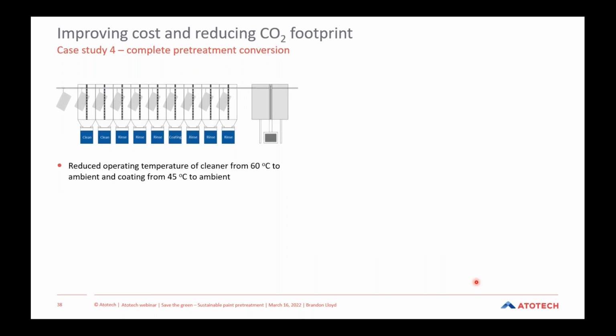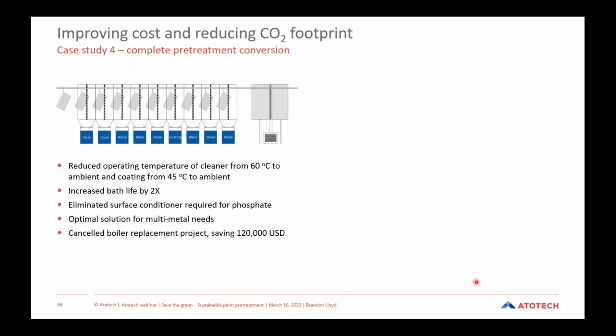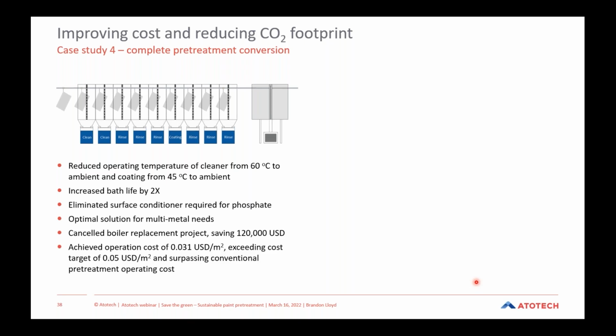With this, they were able to reduce the operating temperature of the cleaner from 60 C to ambient, and for the coating from 45 degrees C to ambient temperature as well. This increased their bath life by 2 times. They were able to eliminate their surface conditioner, which was required for the phosphate process. Again, it was optimal for their multi-metal needs, and it was able to support the applicator to completely cancel their boiler replacement project, which equated to about $120,000 US dollars per year in savings.